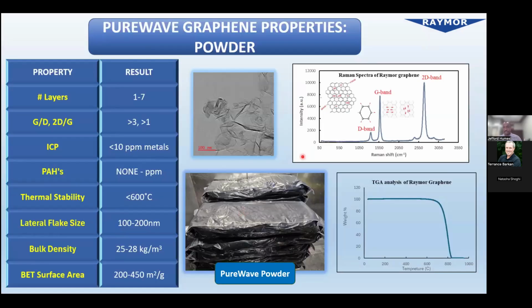In terms of the production technique, the material is produced as it comes straight out of the reactor in the form of a powder, with few layers, 1 to 7, making this a few layer material, with very good G to D and 2D to G ratios, as you can see once again from the Raman spectra. It has very low metals, less than 10 parts per million. And when it comes to polyaromatic hydrocarbons, each batch is produced with no or very little parts per million PAHs. The material is thermally stable, as can be seen from our thermogravimetric analysis, with a stability at or even above 600 degrees Celsius.